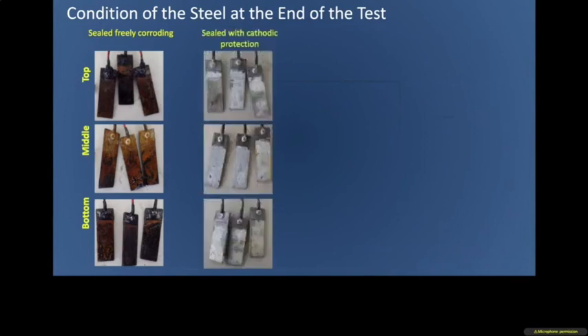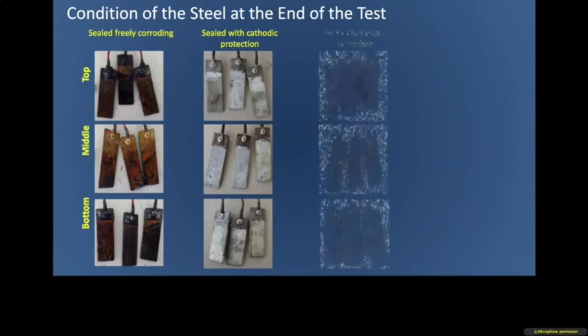So, at the end of the test, what did we see? Our sealed, freely corroding samples all showed corrosion. They actually had black corrosion products, which is typically iron sulfide, the sort of corrosion that one does not want. In the sealed pipes with cathodic protection, we actually prevented corrosion totally, and the white form there is actually zinc carbonate. So that was kind of interesting.